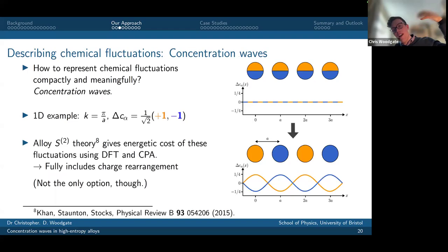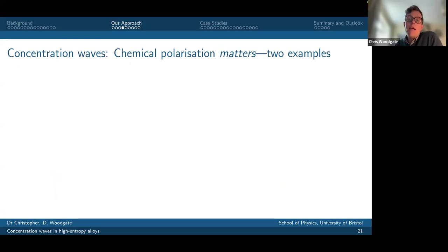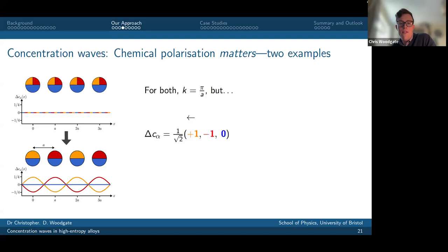Okay, so before I move on, I just wanted to give you some examples. This was an example of a concentration wave in a binary alloy. But let me talk about concentration waves in the multi-component setting, because I want to give you 2 examples here. I'm going to give you 2 1D examples where the wave number describing the concentration wave is pi over a, but where the ordered structure is different. The first example on the left is a 3-component alloy where I have 25% orange atoms, 25% red atoms, and 50% blue atoms. On the left, the concentration of my blue atoms is remaining unaffected, but the concentration of orange and red atoms is alternating. This is described by a concentration wave with chemical polarization +1, -1, 0.